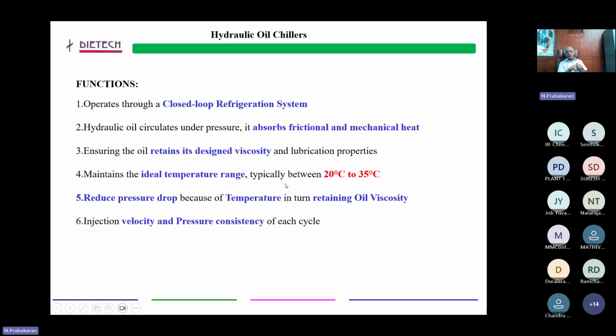It maintains the ideal temperature, typically between 20 to 35 degrees. And it is even possible to bring it down below the atmospheric temperature. Suppose we want to slightly increase the injection force by 2 or 3%, or even 5 or 10% consistently. If you want more, then we can think of even reducing the oil temperature and getting more force inside.